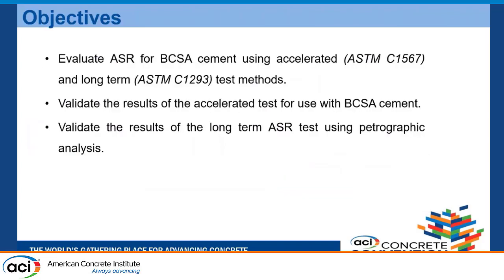And to state the objectives: the first is to evaluate ASR for BCSA cement using the accelerated test ASTM C1567 and the long-term test C1293. The next is to validate the results of the accelerated test for use with BCSA cement. And the third is to validate the results of the long-term test using petrographic analysis.